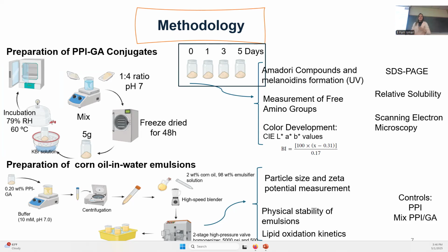Just a side note here, the 79% relative humidity is really high. It's usually not used this high because it can lead to advanced stages of the Maillard reaction. Usually we target lower relative humidity than that. So then after they prepare these conjugates, they analyze the Amadori compounds and the melanoidins formed through UV-vis absorption. They also measure the free amine groups. They look at the color. They calculated the BI, which is the browning index. They look at the SDS-PAGE, relative solubility, and the surface morphology through SEM. After that, they also prepare the emulsions.